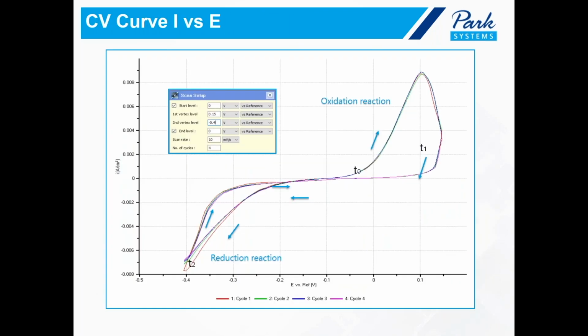All right, I just want to draw your attention back again to the CV curve that we have acquired with the potentiostat. Again, 4 complete cycles of oxidation and reduction were performed. For reduction, we did 2 linear negative sweeps. And for oxidation, we did 4 linear positive sweeps. So it took a little bit more tests to remove the copper particles off the sample surface, but eventually we have successfully removed them all on the gold surface. So the results we acquired in the experiment simply imply that the redox process is reversible depending on the amount of voltage or potential applied in the solution.